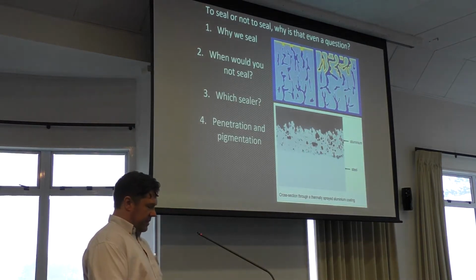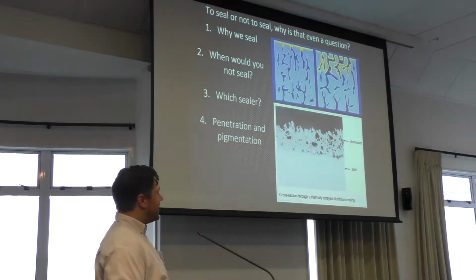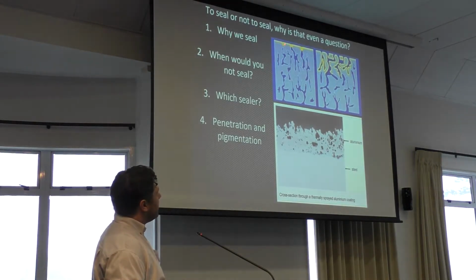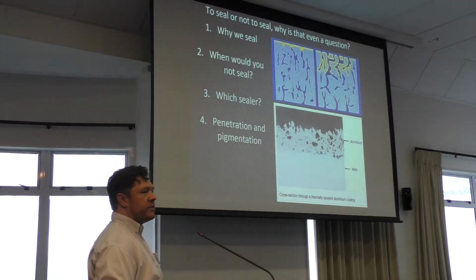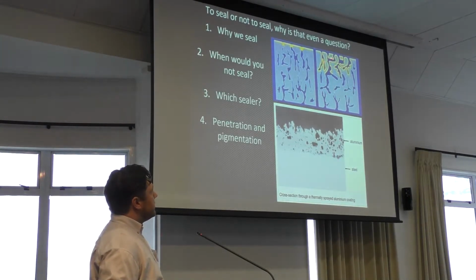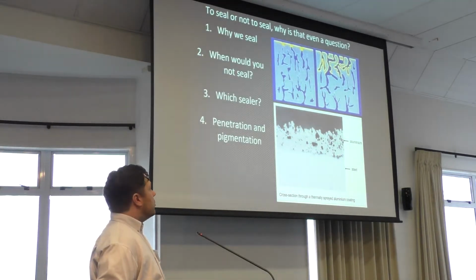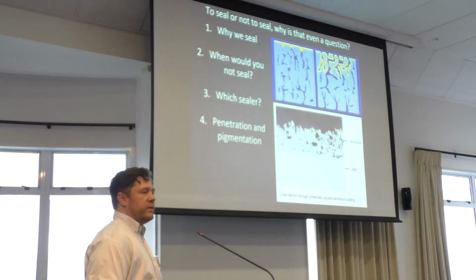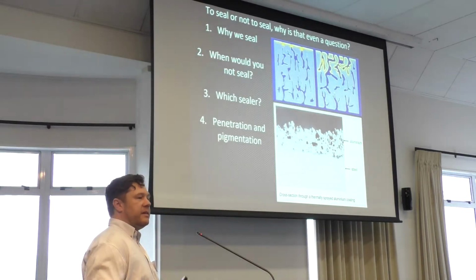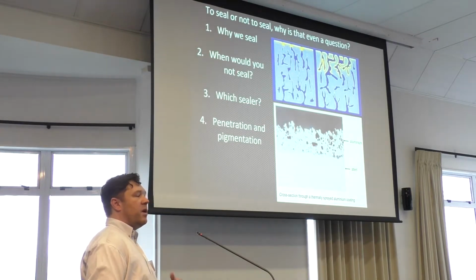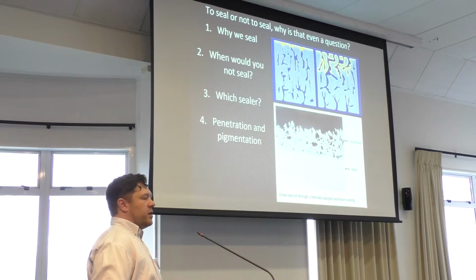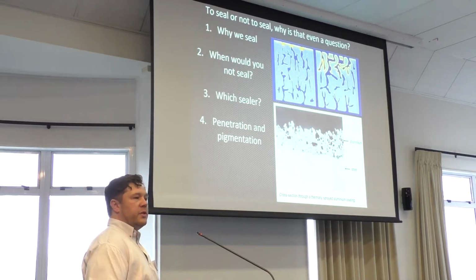Penetration and pigmentation. So this is the wrong picture, it's for the other speech, but you can see here the sealer is sitting very much on top of the coating and it's not penetrating into the pores. This is showing the sealer penetrating in. Ideally we'd like to see it right to the substrate, but if we don't get penetration into the coating like that, we are trapping air in the coating and it's not ideal. So we must thin any sealers that we're going to put on there, basically to the maximum that manufacturers will let us thin it, and then apply more than one coat. So if you're using, say, a 40% volume solid vinyl and you thin it 30%, we're down to a 30% volume solid coating. Obviously 60% of that's going to evaporate off, so you'd expect at least 3 coats of thin sealer to fully seal that coating.